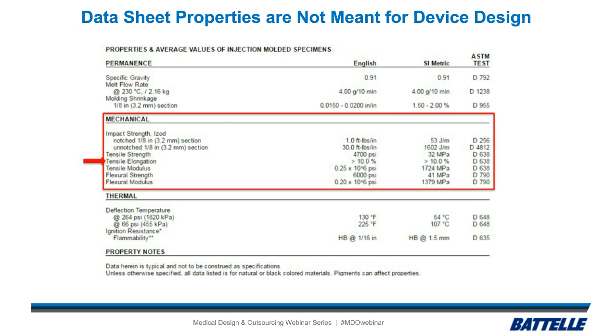The next thing on here is tensile elongation, and this one's a bit vague, so it says it's greater than 10%. It also doesn't say if it's the elongation at yield or at break. So those are two very different things, and we like to design for underneath or less than yield for all of our parts because we don't want to have plastic deformation. Some elastic deformation may be okay, but once you get past that yield point, you don't want to get into plastic deformation for designing a part. So here, again, we don't know what type of elongation, and then we don't know if it's 11% or 1100%. It's greater than 10. So again, just a little bit too vague to really use as a design.